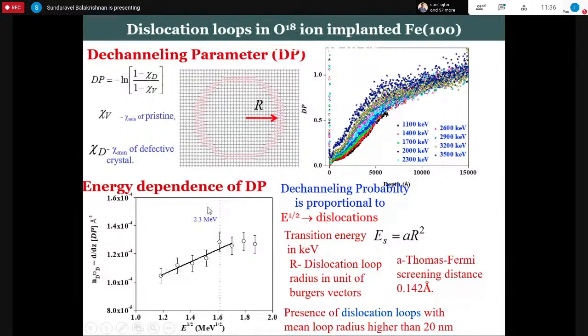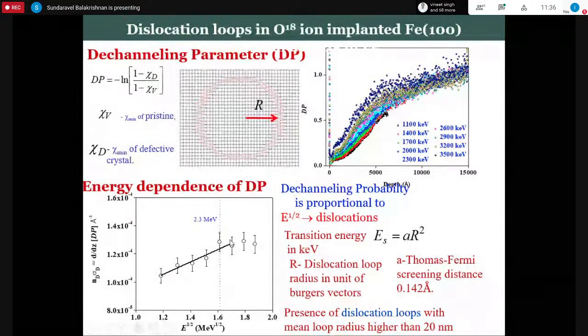And this transition region, in this case it is 2.3 MeV, where you are getting the saturated curve, from that one you can find the radius of this dislocation loop. And in this sample we see that the dislocation loop radius is something like 20 nanometer.